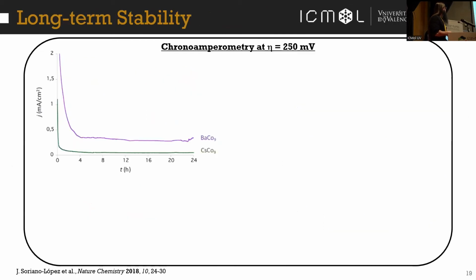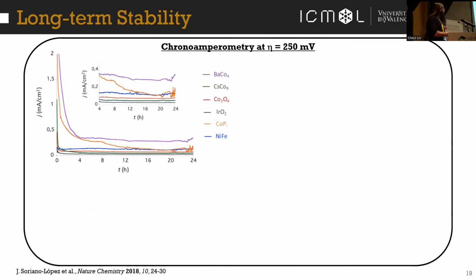So, well, we also studied the long-term stability of these polyoxometalates under these conditions, and we can see that they are perfectly stable for at least 24 hours. And we, again, compare it with other catalysts. So we can see they are more active under these conditions than iridium oxide and cobalt oxide. And we also compare it with the CoPi catalyst.